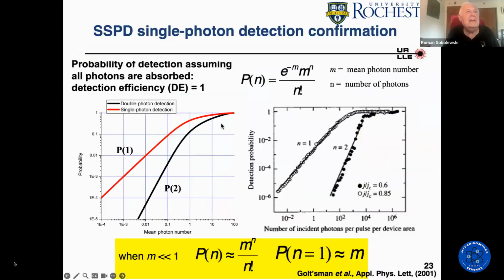I want to stress that if you look at the statistics, and that's simple Poissonian statistics, you see that for a low number of average photons per pulse, the probability of detecting a photon is just proportional to that average number of photons per pulse. So it's single photon detection and two photon detection. And you can clearly see that our experimental results follow perfectly.